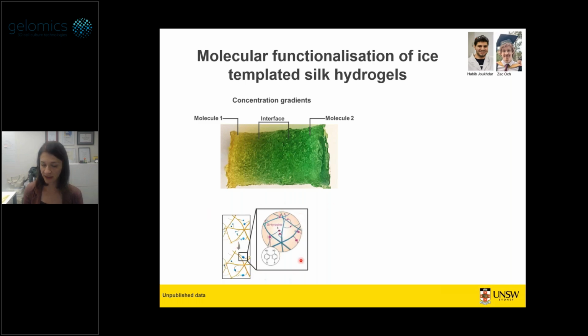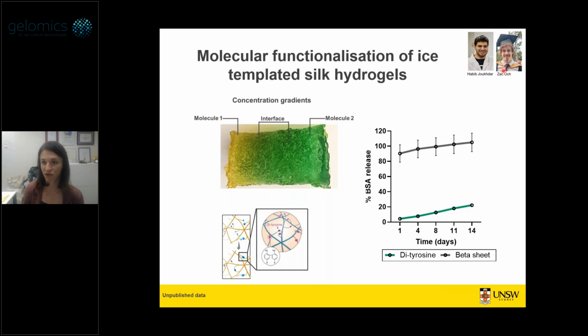And because we're doing this via dityrosine crosslinking, it means that if any of these molecules are proteins, most proteins have tyrosine amino acids, which means we can covalently trap them in the hydrogel. So Zach has shown this with BSA, for example, that if we encapsulate BSA in our beta sheet cross-linked hydrogels, it is released very, very quickly. Whereas if we trap it in our dityrosine cross-linked hydrogels, it actually stays in the hydrogel for a long time. Even this is after photo cross-linking and ice templating.